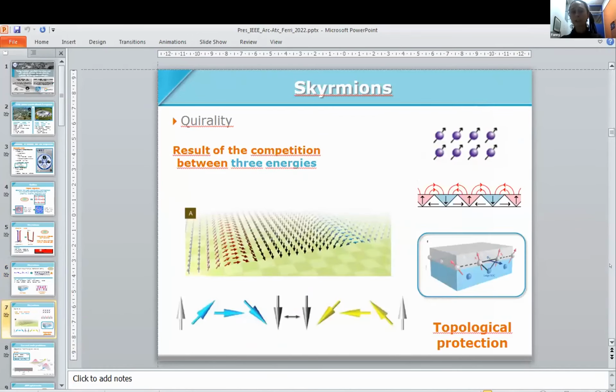One thing that is important about skyrmions is their chirality. Because they are the result of the competition between three energies. Here we have the exchange energy, there's the magnetostatic energy through the stray field and so on. And then we have this third energy that is occurring in the sum, which is the DMI. And because of the helicoidal nature of the DMI and the result of the three, you have a chirality for the skyrmions. This gives the topological protection, but you have a charge that is +1 or -1, which may be a problem.